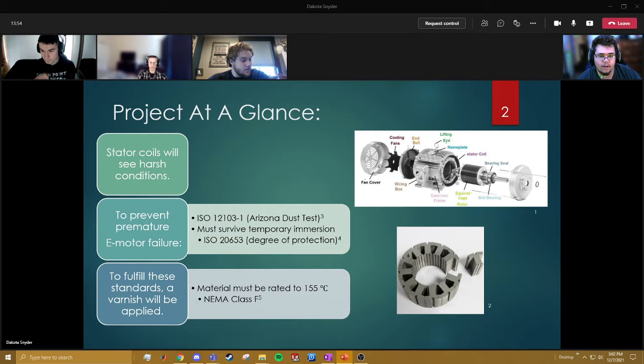to survive temporary immersion. To combat the resulting corrosion because of immersion, a varnish is applied to protect the inner diameter of the coil. This coating will also need to be able to withstand a temperature of 155 degrees Celsius.